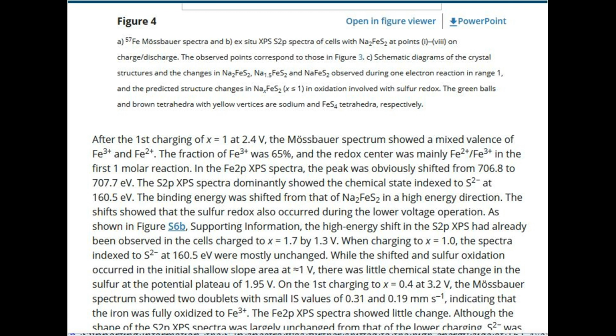After the first charging of x = 1 at 2.4 V, the Mossbauer spectrum showed a mixed valence of Fe3+ and Fe2+. The fraction of Fe3+ was 65%, and the redox center was mainly Fe2+/Fe3+ in the first 1 molar reaction. In the Fe2p XPS spectra, the peak was obviously shifted from 706.8 to 707.7 eV. The S2p XPS spectra dominantly showed the chemical state indexed to S2- at 160.5 eV. The binding energy was shifted from that of Na2FeS2 in a high energy direction. The shifts showed that the sulfur redox also occurred during the lower voltage operation.